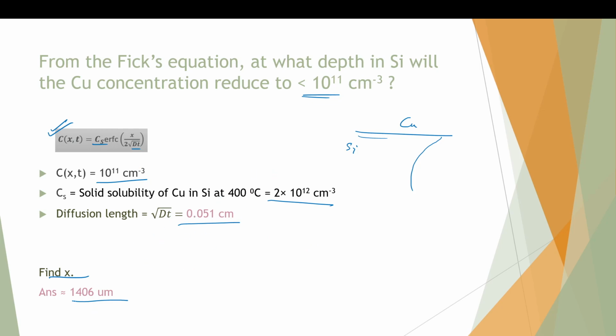So the depth x is 1406 micrometers. An average copper atom could have diffused all the way down to 1406 micrometers, but our wafer is only 500 micron thick. So what does that mean? The copper is all over the wafer now. The impurity has gone all the way through the wafer. That is the problem with copper. Copper diffuses very fast. Forget about the first 10 microns, it has already covered the entire wafer.